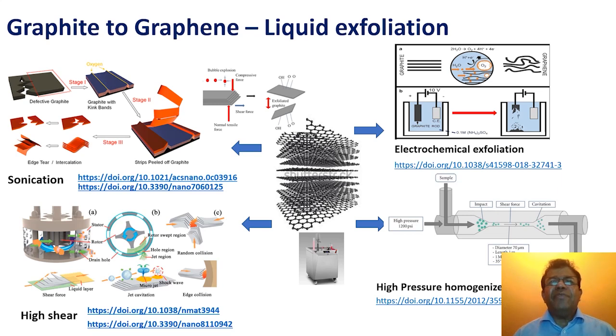Graphene production from graphite via the top-down route has many unique advantages and is based on the one-step physical transformation of graphite into graphene. However, pristine graphene production has been pursued with difficulties either in production rate or in the number of layers present in each graphene platelet. Liquid phase exfoliation from graphite to graphene requires input energy to overcome forces between the layers. The required energy is provided by various means such as sonication, electrochemical energy, mechanical energy or high pressure to break existing interlayer interactions.